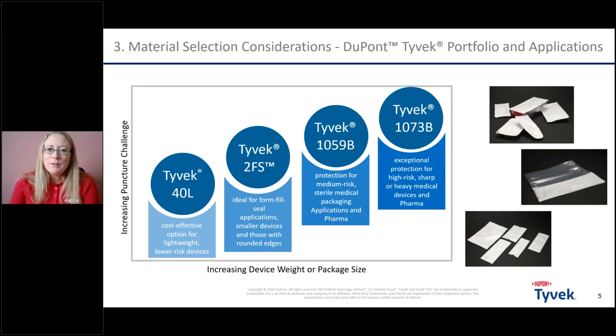On the right side, you can see some pictures of the packaging configurations I've just mentioned. You have rigid trays, for example, or form-fill-seal packaging, so thermoform trays with some lidding material, which can be Tyvek or medical grade paper. Then in the middle, you have a so-called header bag, which is three-quarter film with a porous Tyvek window, which allows for gas sterilization. And down below you have an example of 2D packaging, so flat pouches, usually with one side porous material and the other side film.